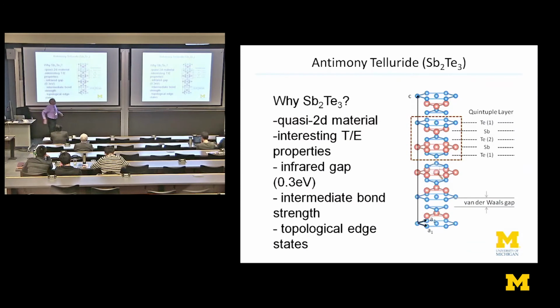Before I get to that question, let me just say something about why we were interested in antimony telluride here. Well, firstly, because it has an infrared gap of about 0.3 eV, so it's in the mid-infrared region. There are many applications that are interesting for sensors in this region of the electromagnetic spectrum. The material also has a kind of intermediate bond strength. It's not a very strongly bonded material. It's perfectly stable, but it can be modified using the electric field in a laser